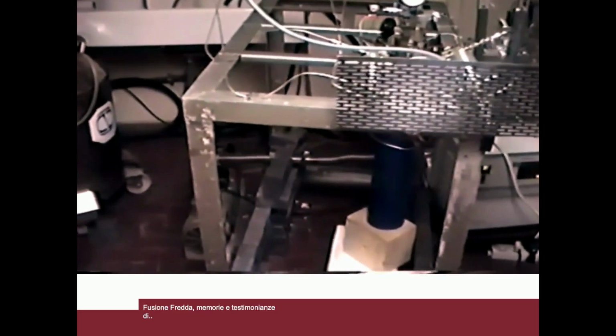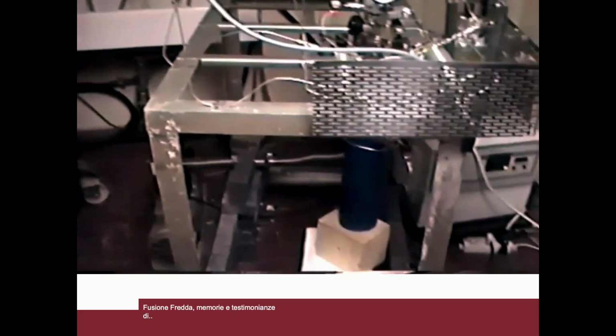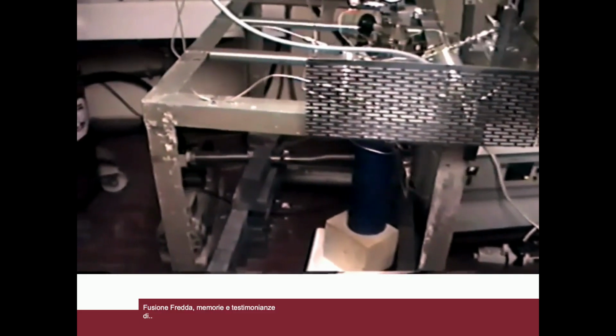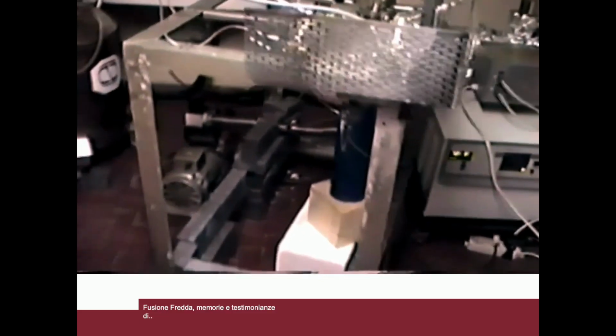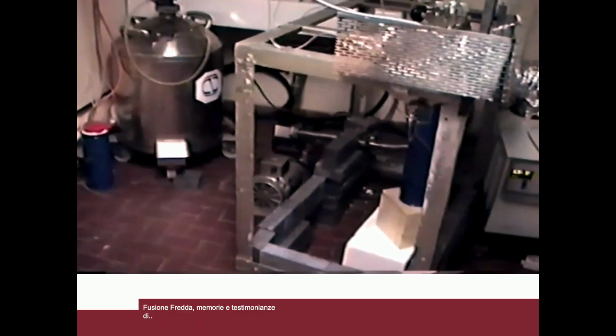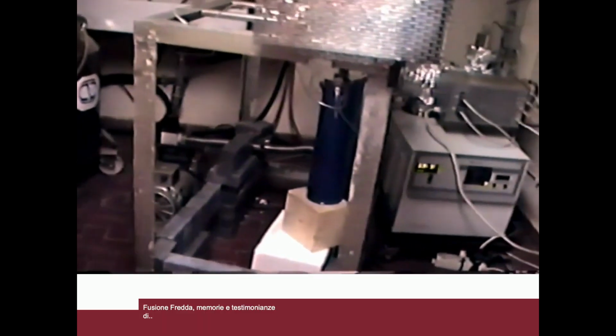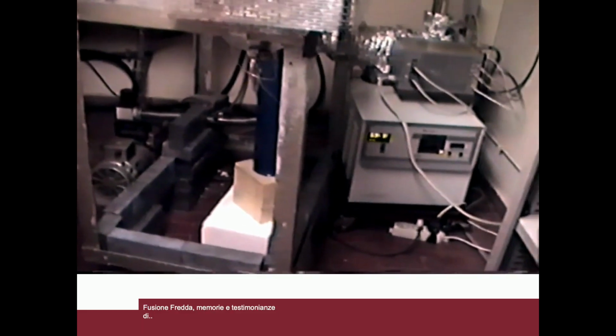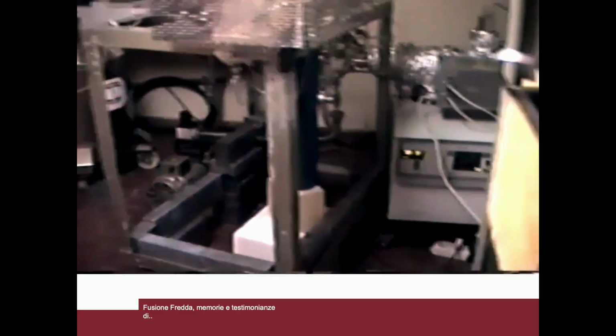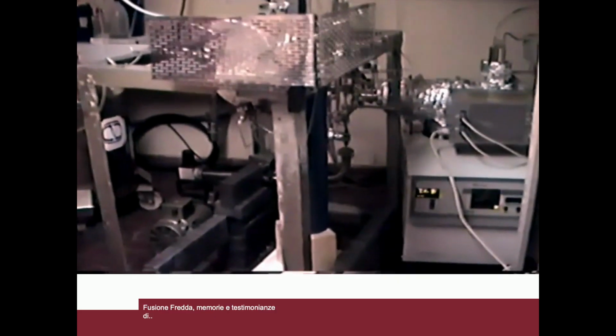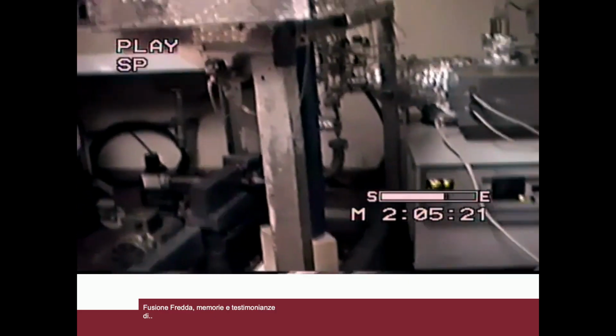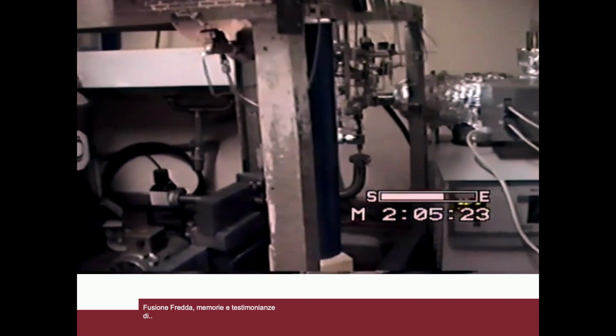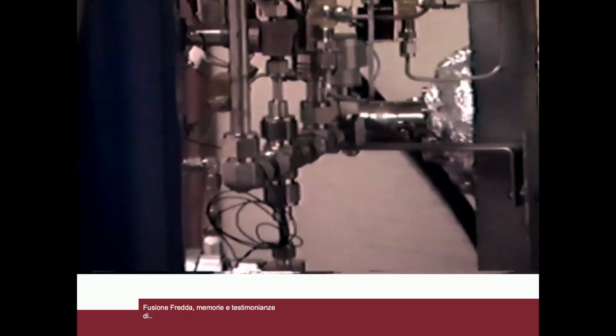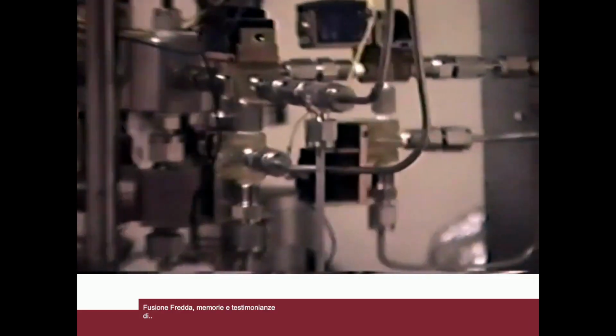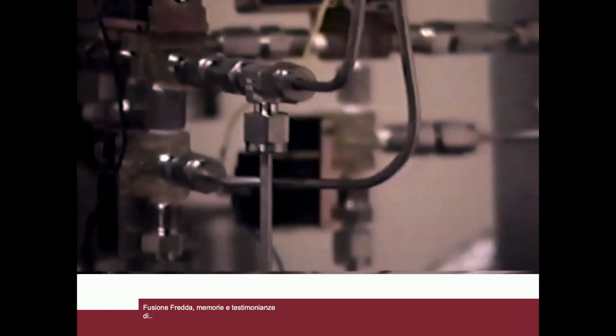The function of these 2 stages is to drastically reduce the deuterium content to make possible the determination by mass spectrometry of helium-4, especially if in trace amounts. As seen previously, the mass spectrometric separation of deuterium from helium is critical. The introduction of gas into the mass spectrometer is regulated by a low vacuum system such as to create the optimal working conditions in the spectrometer chamber.